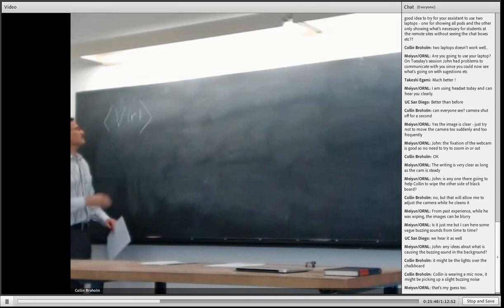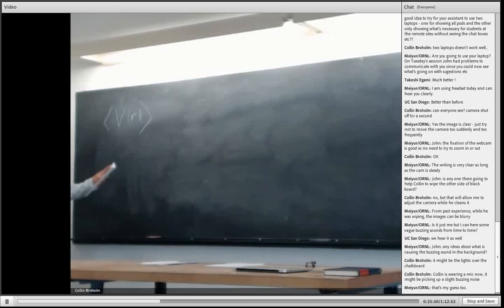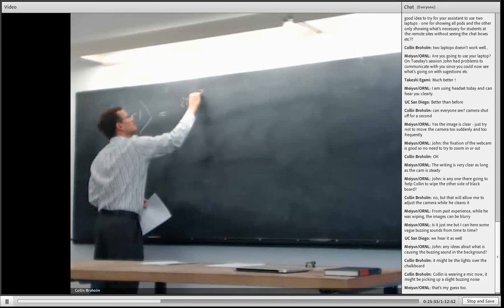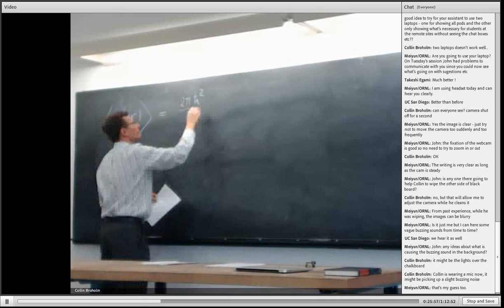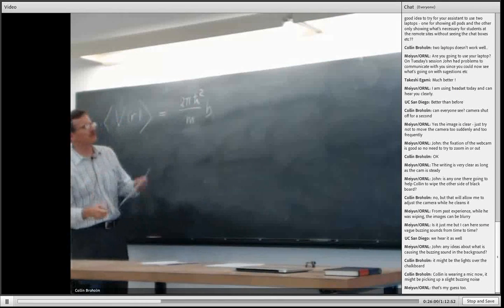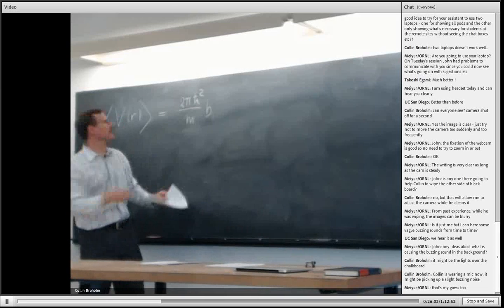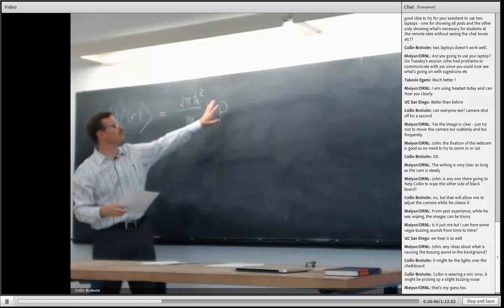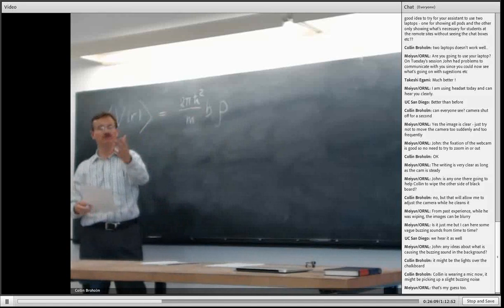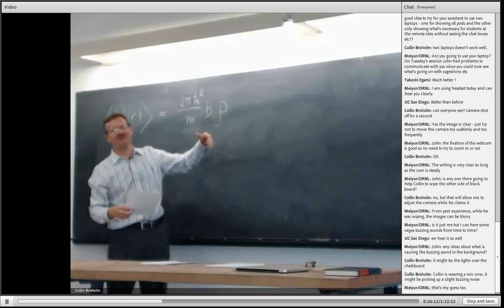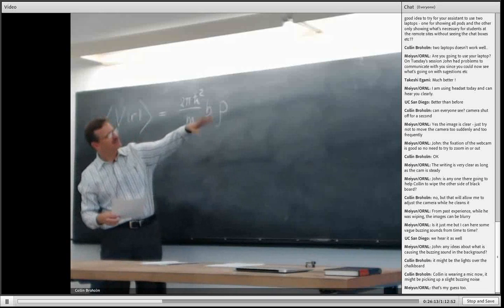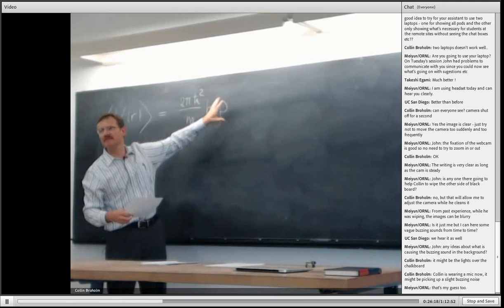So I'm going to do the normal trick that we do in electromagnetism, and that basically ends up replacing the Dirac delta function in my pseudo potential by the nuclear density. Here we have to be careful, because my nomenclature previously had a rho in it, which was the density of neutrons. But now I like rho so much that I'm going to reuse it, having dispensed with that part of the calculation, to talk about the nuclear density in the material. So that is now what the potential is.